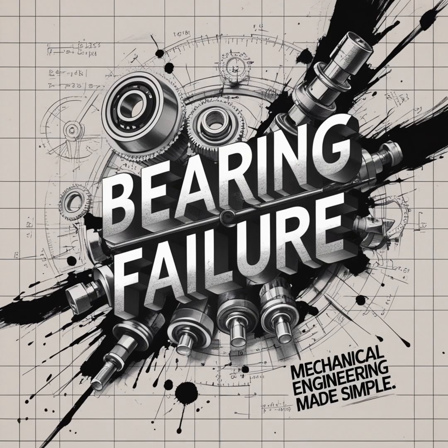Wouldn't more grease mean more protection? It seems counterintuitive, I know, but no. Excessive amounts of grease, or over-greasing, causes a rapid rise in operating temperature, especially at high speeds. Right. The bearing elements have to literally churn through this dense block of lubricant, and that generates immense heat. We call it churning. And that heat just destroys the lubricant. It degrades it chemically, which reduces its effective viscosity, and that leads directly to premature failure. So quantity is one thing, but you said viscosity is king.